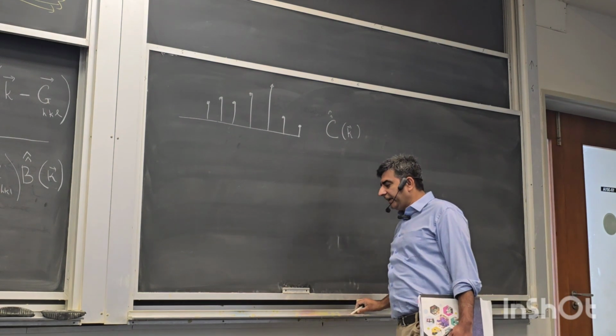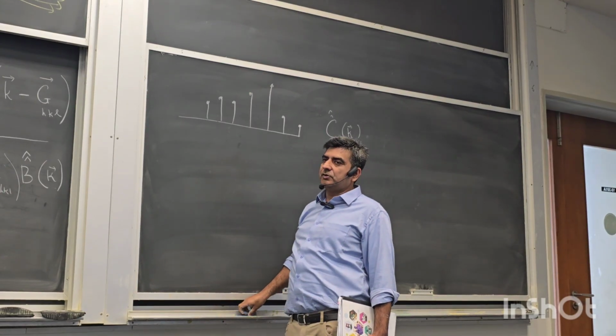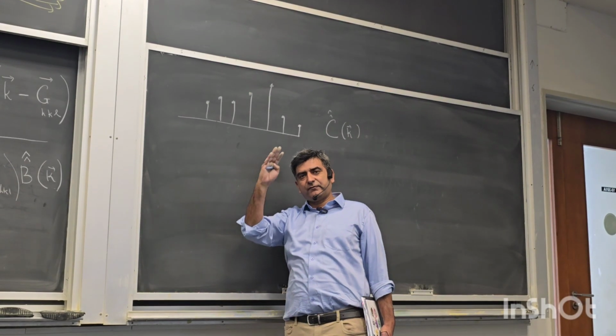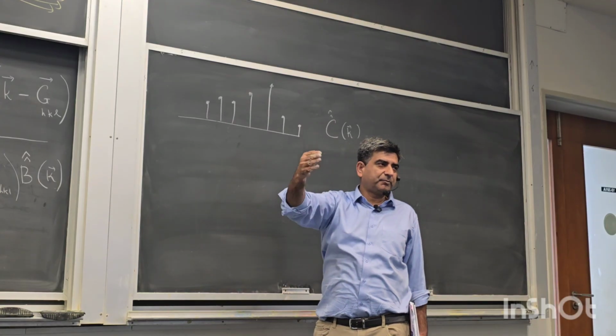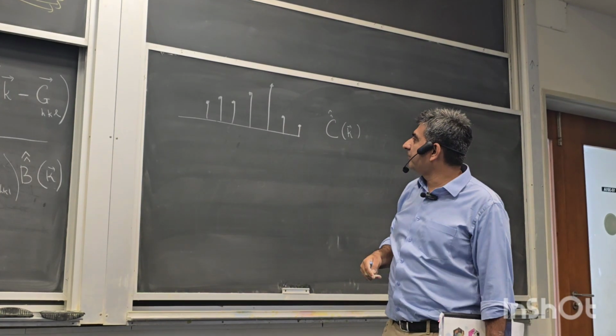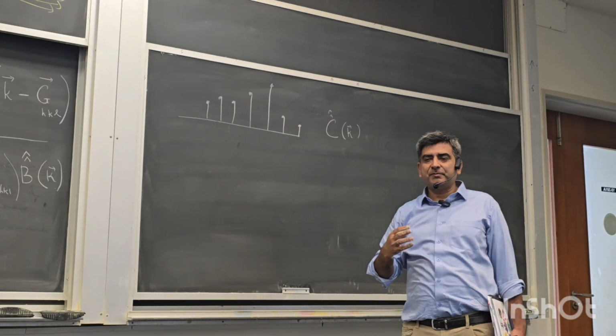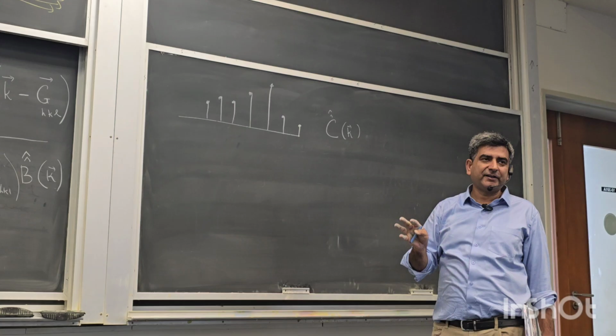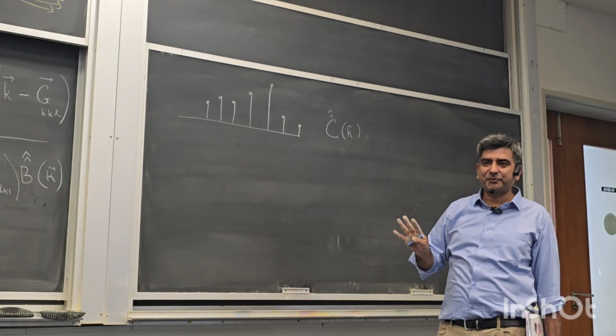All right. In fact, the Fourier transform of the entire crystal structure is the motif Fourier transform sampled at the reciprocal lattice points. Now, another thing that you would like to mention is that whenever you see a spectrum, I need to relate this to the diffraction spectrum that I haven't done at the moment, but so far so good.